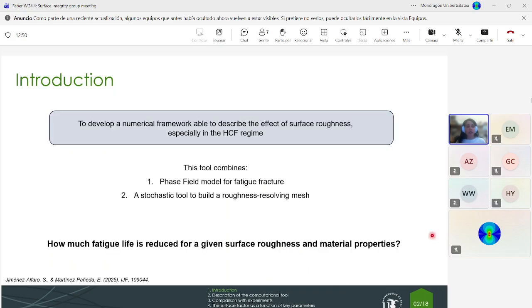So in this context, we propose to develop a numerical framework that is able to describe the effect of surface roughness, especially in the high cycle fatigue regime. And this numerical tool is a combination of two different techniques. One is the phase field model for fatigue fracture, and the other one is a stochastic tool to build a roughness resolving mesh. So in the end, what we want to answer is the question how much fatigue life is reduced for a given surface roughness and material properties. And this is the work that we have recently published in International Journal of Fatigue.